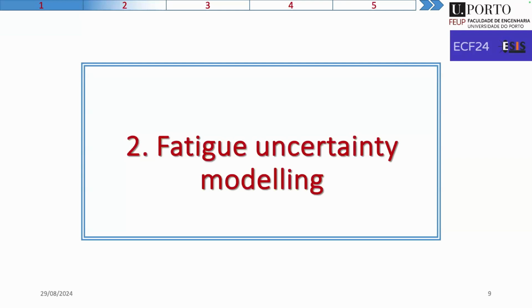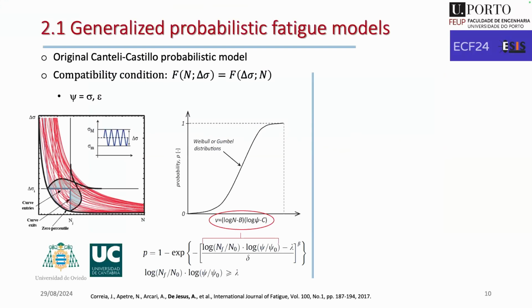So, as I told you, our work has been done in collaboration with different partners across the world. So we started a collaboration about 20 years ago with Professor Canteli and Professor Castillo from the north of Spain. They developed a very simple and powerful probabilistic model based on the well-known Weibull distribution, but for fatigue analysis. And the most interesting part was that this model is able to predict the full S-N field, not only the fatigue life distribution for a given stress or the strength distribution for a given fatigue life. It really predicts the complete field.